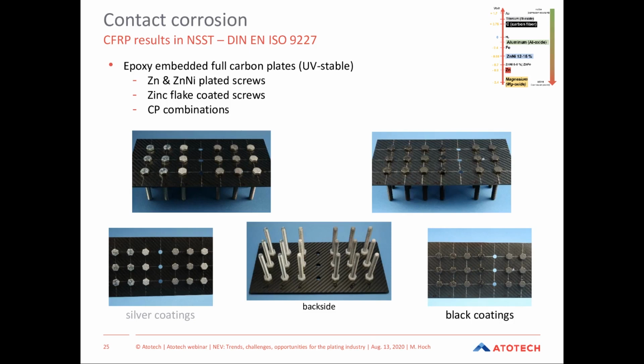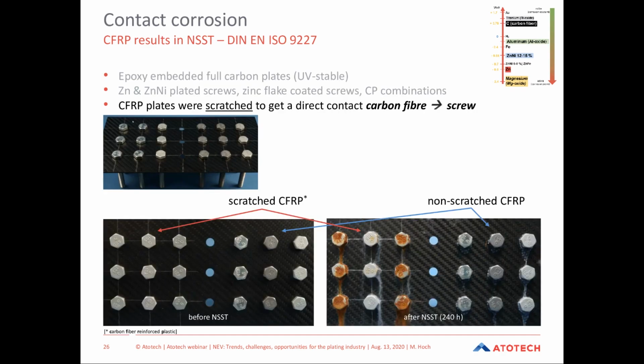In our tech center trials, we used epoxy-embedded carbon fiber boards, in which we placed screws plated with zinc and zinc nickel, coated with zinc flakes, and additionally with different CP combinations. We did silver coatings, which you always see on the left side on my slides, and we did black coatings, which are shown on the right side of the slides. All screws were fixed with plastic nuts, which is seen in the middle, which is called backside. The carbon fiber boards were then put into the neutral salt spray test up to 240 hours. And the results will follow in the next slides.